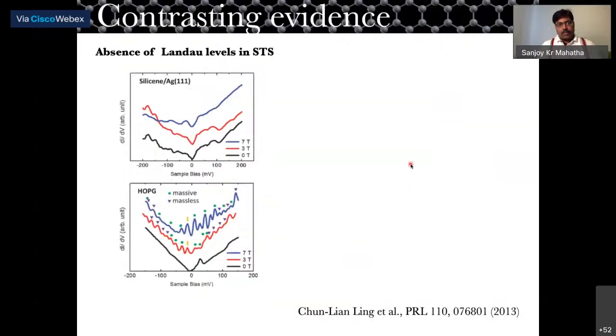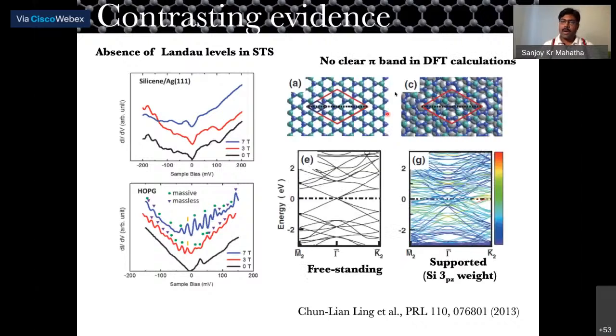But a few other groups did the same experiment using scanning tunneling spectroscopy. They could not find any signature of a linear band in silicene. They couldn't find any signature of a Dirac cone, and there was also no clear pi band in DFT calculations. So there are no clear bands. There are a lot of foldings because of this 4 by 4 or root 13 structure, but there is no clear indication that there is a Dirac cone coming from silicene.